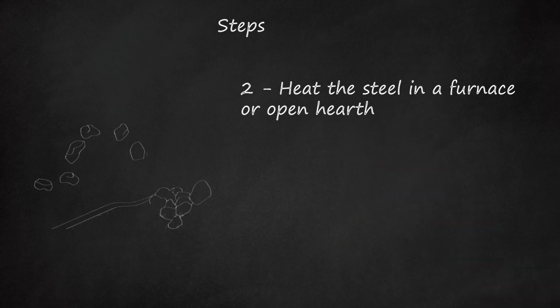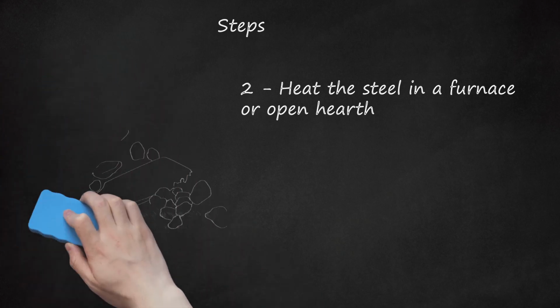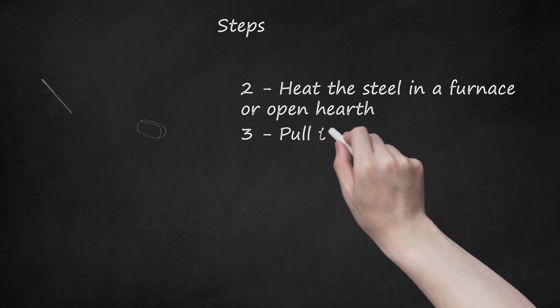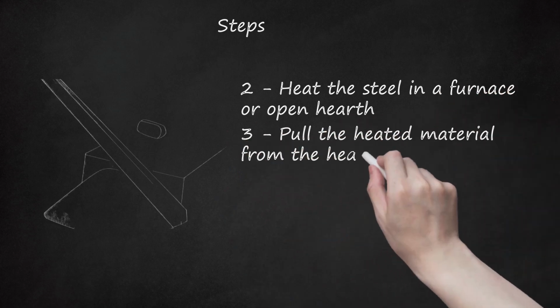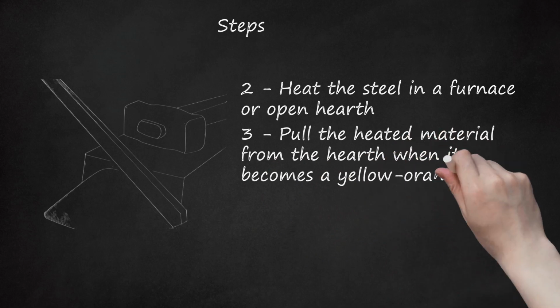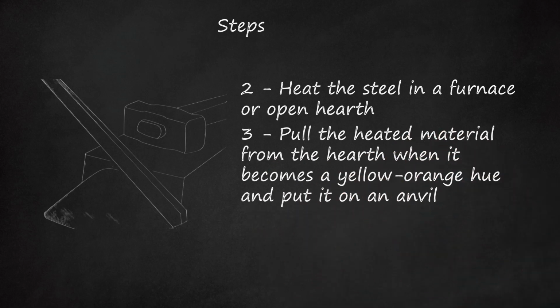You must heat the material to temperatures nearing 1600 degrees Fahrenheit, 870 degrees Celsius, to make it malleable for forging and to remove impurities. During the heating process, substances like sulfur and silica will oxidize and separate from the iron, creating slag. The removal of slag greatly strengthens the steel. 3. Pull the heated material from the hearth when it becomes a yellow-orange hue and put it on an anvil.